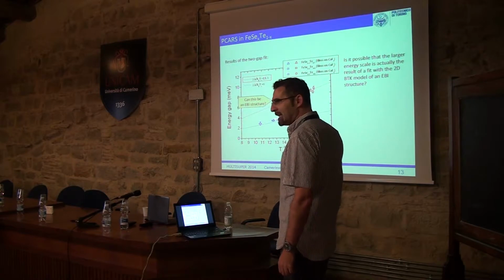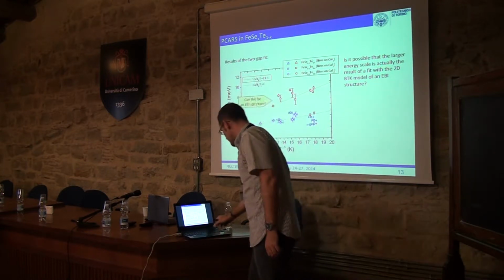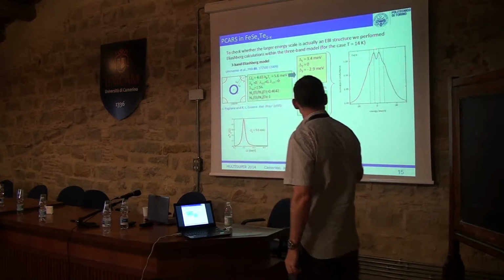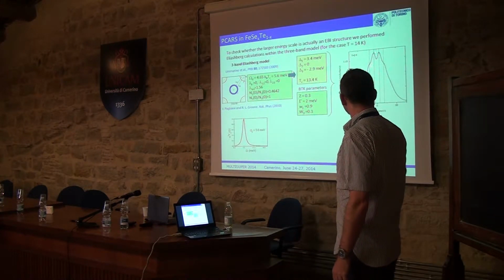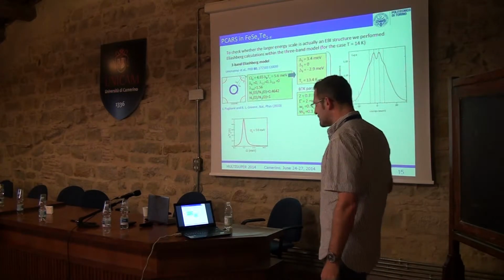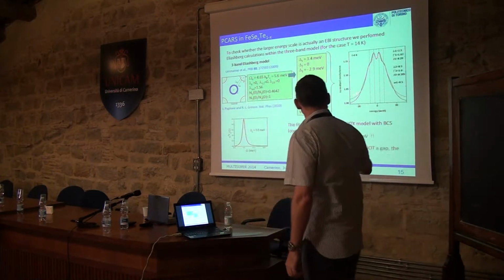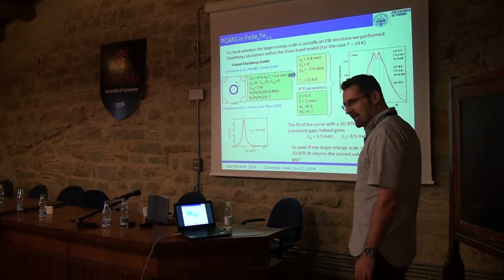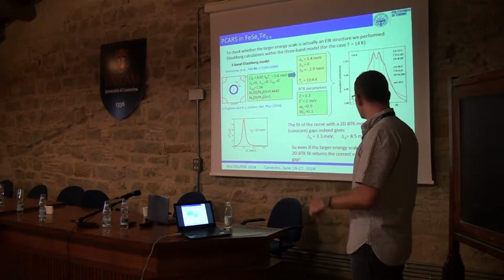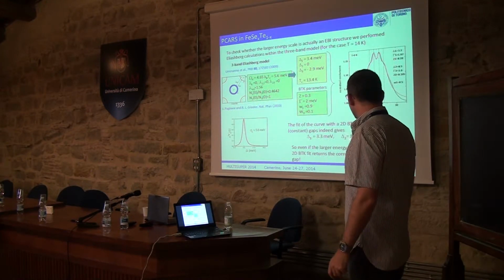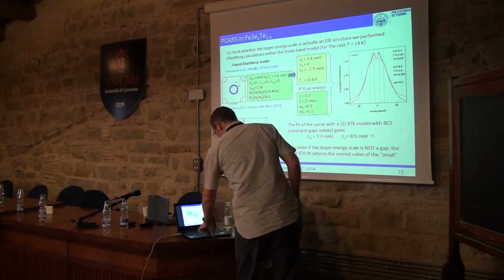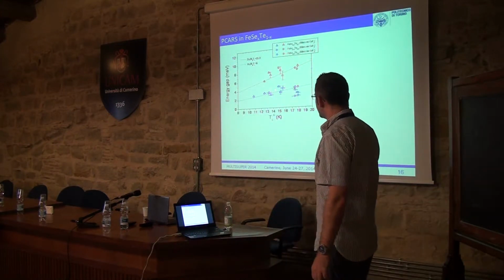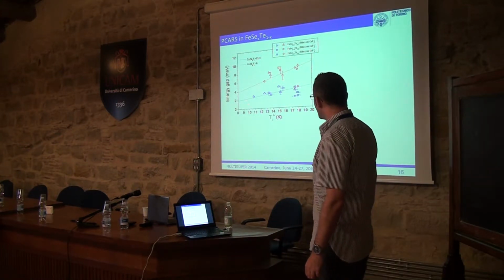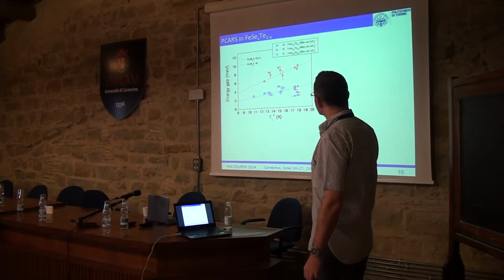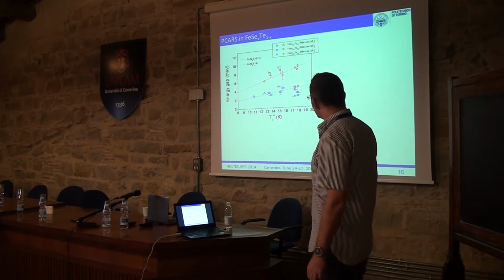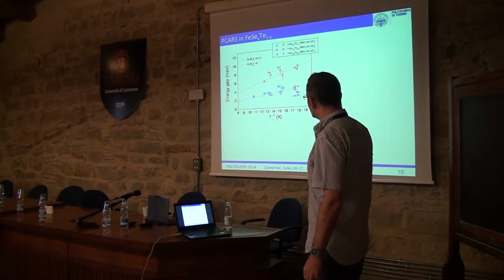So supposing this is really a gap, what is the position of the electron-boson structures? The answer is that this is the curve. So the gap is this one. These are the electron-boson structures. And if we fit this curve by using the two-band BTK model, this is the red line, we obtain a gap which is exactly the gap we have put in. So it's the real gap, plus a fake gap at 8.5. This means that going back to our picture, this is really a gap, this is not a gap. And so we have only one gap that seems to have 2Δ over kTc of the order of 6. But what happens here? Because we have blue and red data.